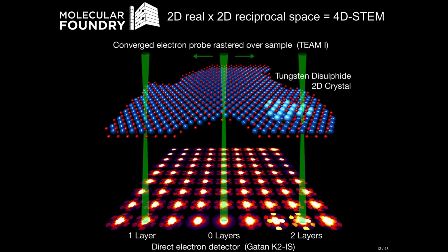This is one of our first experimental data sets on the TEAM 1 microscope, an aberration corrected FEI Titan microscope. It's on a two-dimensional material, tungsten disulfide. Part of the sample was single layer and part of it was two layer. And if you look in the far field, you can see each of the diffraction patterns contains that local crystallographic information. You can see the difference between a zero layer unscattered probe, where it's passing through a hole in the material on the center beam there. On the left-hand beam, you can see where it passes through a single layer, and on the right-hand beam, where it passes through two layers. So it's very easy in this case to see the difference between one layer and two layer just from the diffraction pattern alone. But this image doesn't really show the whole story.